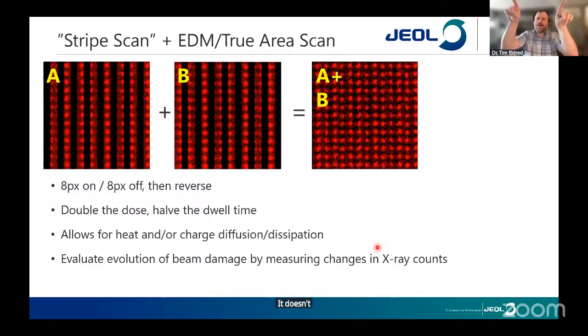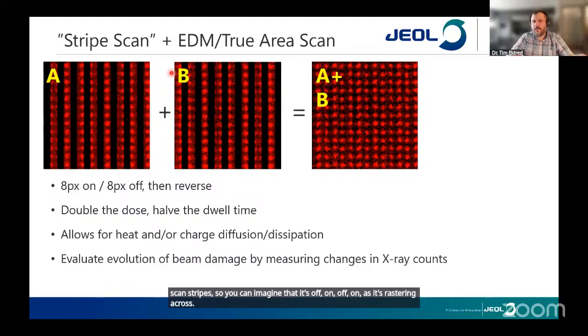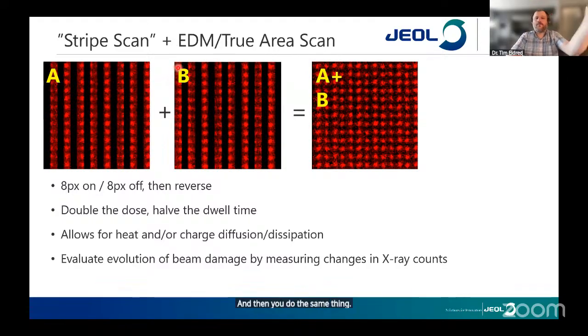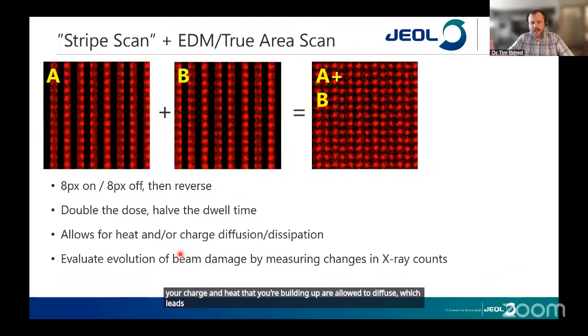It doesn't have to be this crazy distribution. You can also scan stripes. So you can imagine that it's off, on as it's rastering across. And then you do the same thing, but you change which ones are on and off. This gives you the same information, but you're doubling the overall dose to your sample. But because you're applying it in a different way, your charge and heat that you're building up are allowed to diffuse, which leads to less radiolysis and less damage.